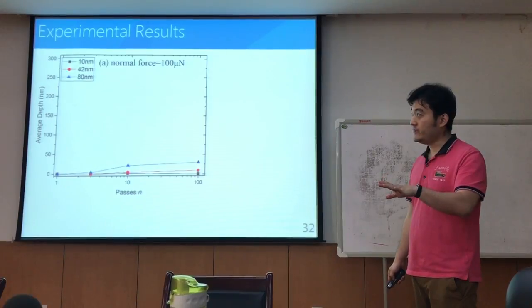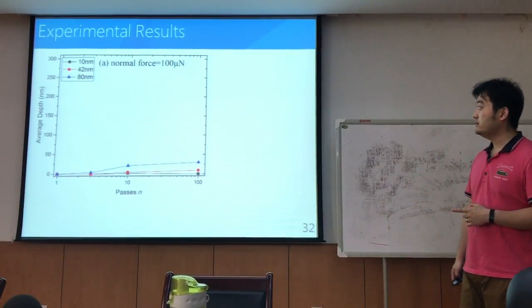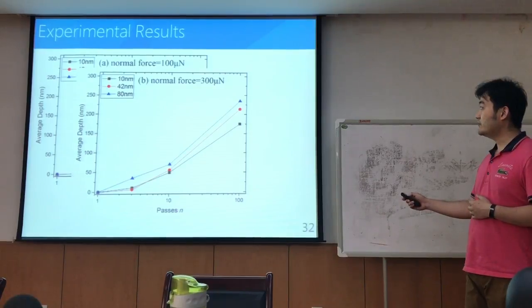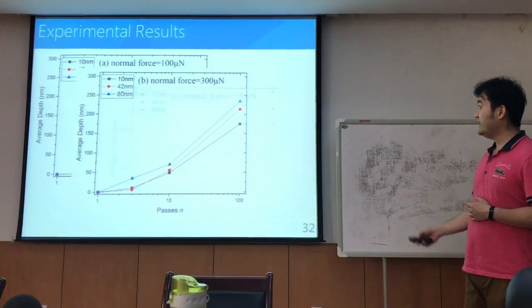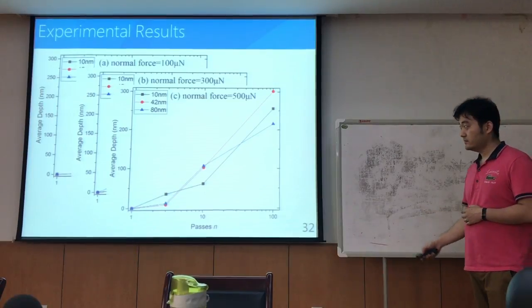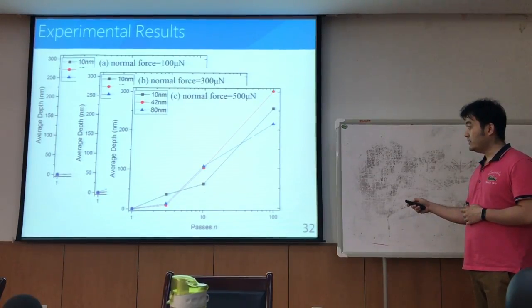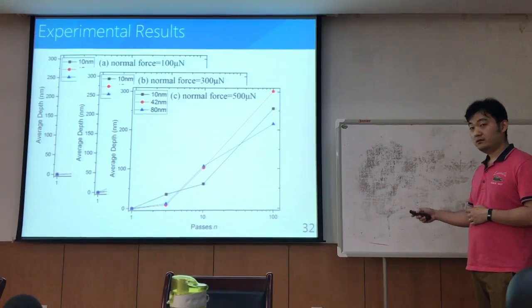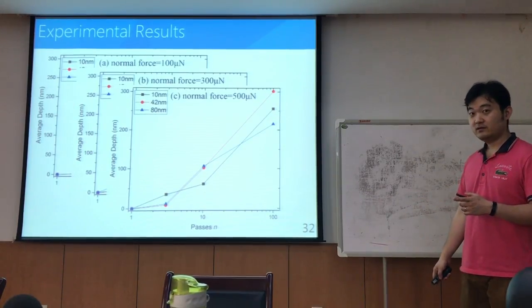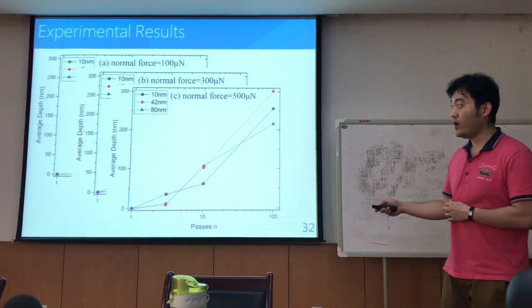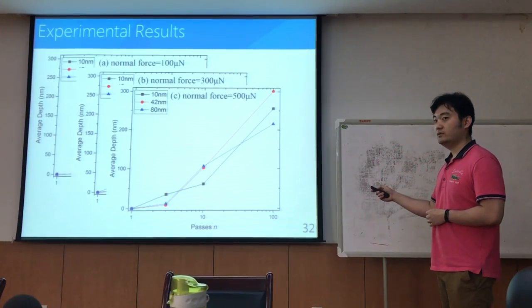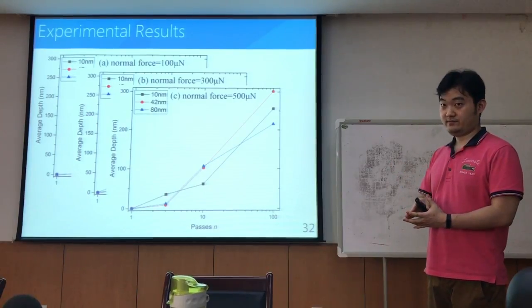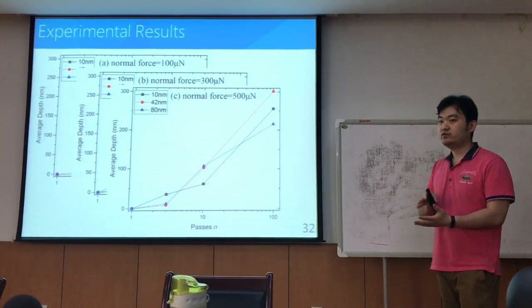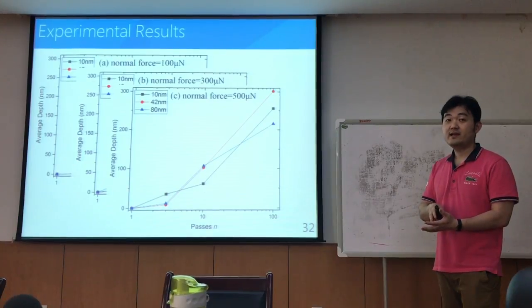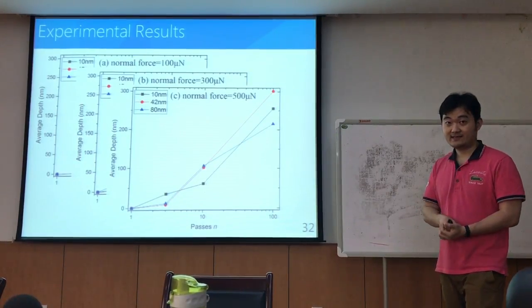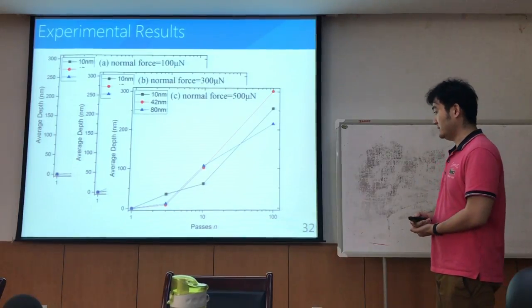But when we increase the normal force from 100 micronewton to 300 micronewton and to 500 micronewton, the 80 nanometer grain size specimen performs the best. This is because when we increase the normal force, the phase transformation will be involved. And this phase transformation will increase the contact area, which makes the contact stress become less. And this is good for wear resistance.